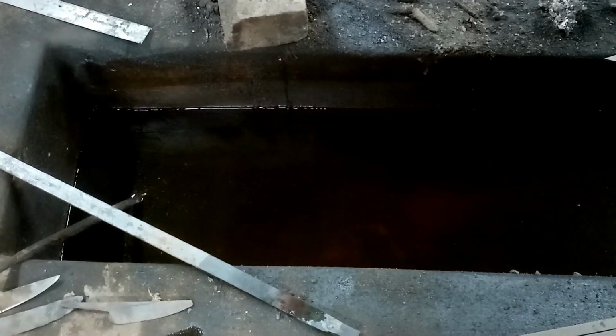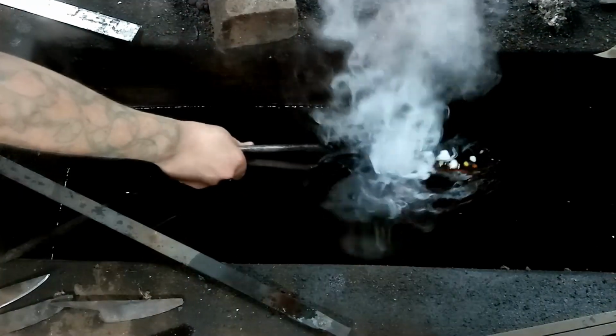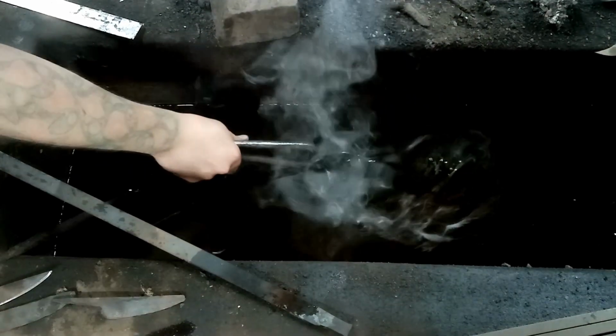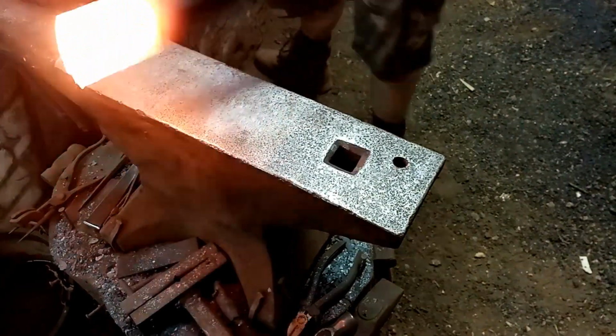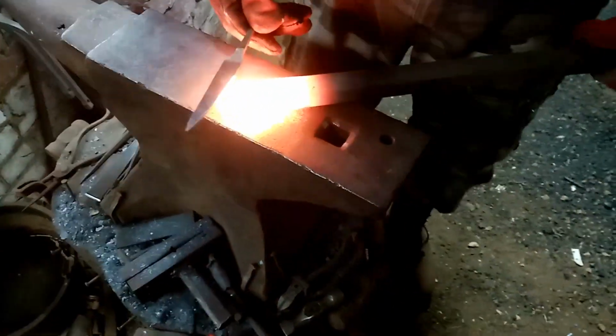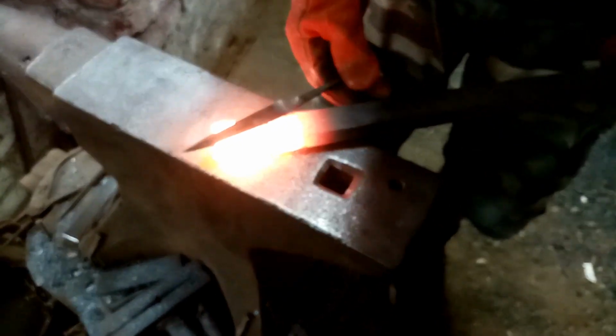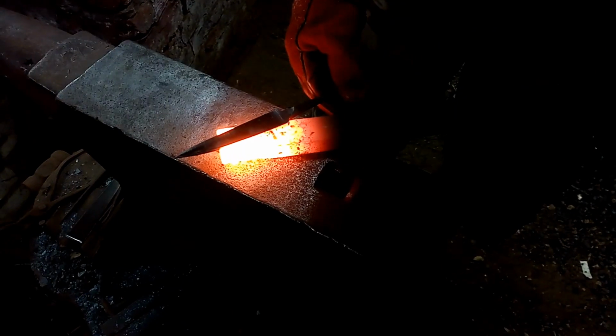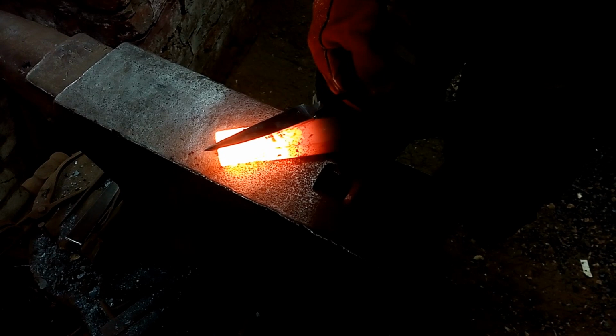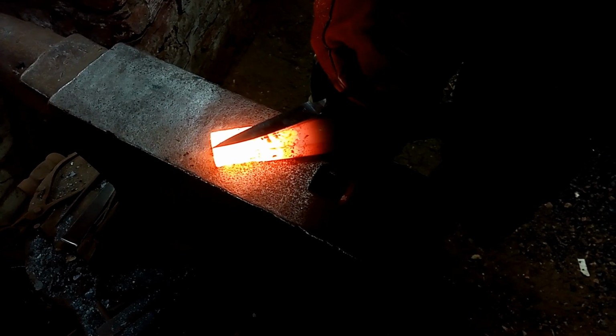Again, heat that blade up to above critical temperature, so in this case 880 degrees. Bring him out of the fire, straight into your oil. Don't use water on this spring, use oil. Keep the blade nice and straight when you do, and shake it to make sure no bubbles form, causing uneven quenching across the blade. Once you have quenched it and hardened it, clean him up again so when you temper him, you can see temper colours move through.